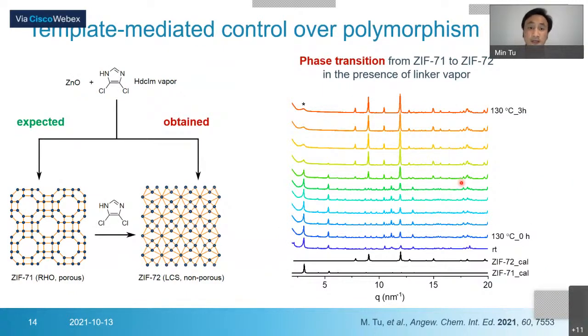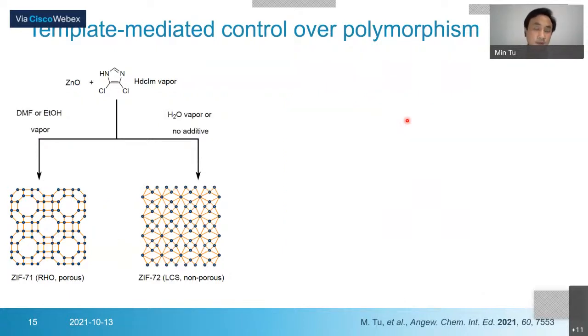Then we performed another measurement to confirm our hypothesis. We first made ZIF-71 by solvothermal synthesis. Then we reacted it with this linker. We didn't do any other reaction. We just placed ZIF-71 and this linker together at a relatively low temperature, 130. Within a few hours, this ZIF-71 converted to ZIF-72, which also confirms that ZIF-71 is the kinetically preferred phase, but ZIF-72 is the thermodynamically stable phase. So the question comes to us: how can we get the ZIF-71 we wanted? We came up with an idea to have template-mediated control over this polymorphism.